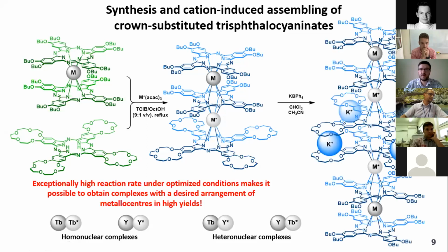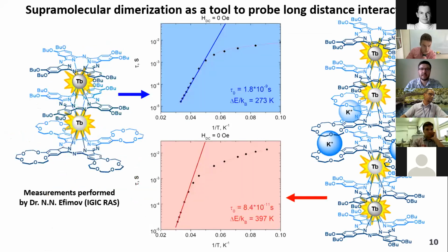Similarly to the previously studied complex, we found that it can form supramolecular dimers in the presence of potassium tetraphenylborate, and we studied it by various physical chemical techniques. Here we have the results measured recently by Dr. Nikolai Efimov from Kurnakov Institute, who showed that going from monomeric triple decker to dimeric 6-decker complex with 4 terbium ions has a profound effect on the growth of the relaxation barrier. So by the moment, as far as I know, this value is the largest in complexes formed by binuclear triple decker phthalocyaninates.